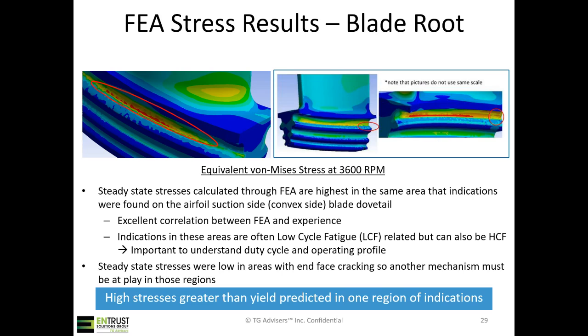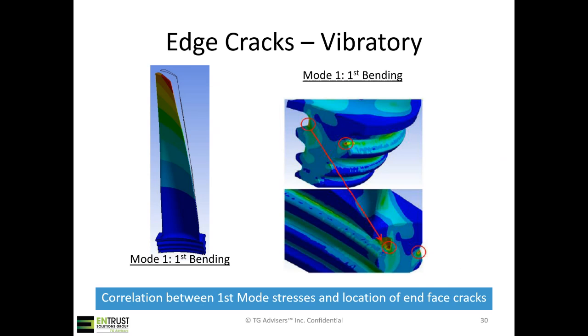The indications on that convex side in those areas typically are low cycle fatigue related, but they can also have a high cycle fatigue interaction too. So it's important to understand the duty cycle and operating profile of the unit. Because those steady state stresses were low in the areas with end face cracking, though, we had to figure out what could be driving those cracks. And so that brings us back to vibratory stresses and our natural frequency and mode shape analysis.